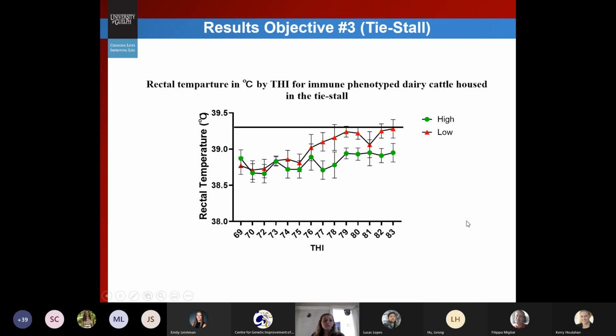And then when looking at results for rectal temperature, again, we didn't see a significant difference between the phenotypes for rectal temperature. And in general, most of the cattle did remain within normal ranges across the study. But one thing I did want to point out, again, when we look at that THI of 76, that seems to be where our low cows are having an increase in rectal temperature relative to the lower THI values.